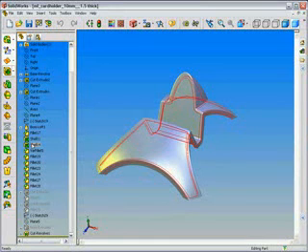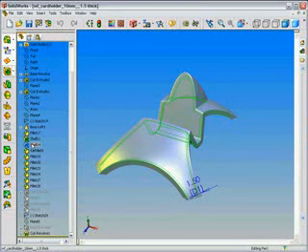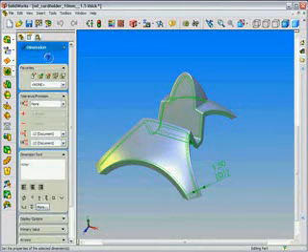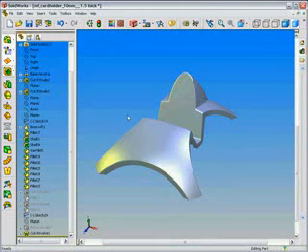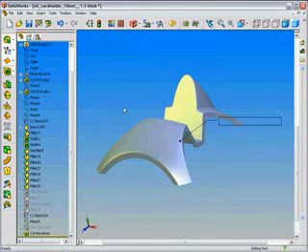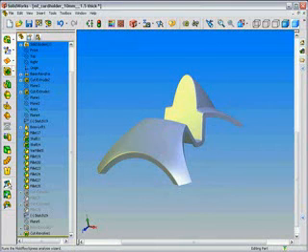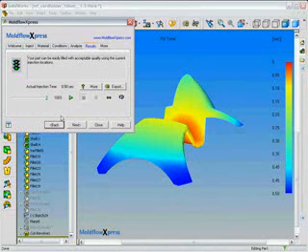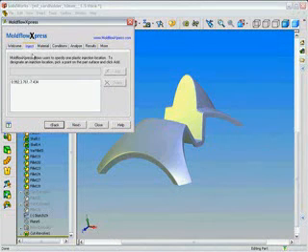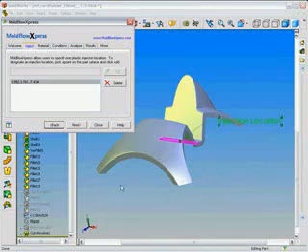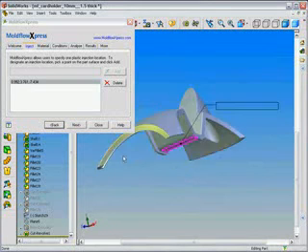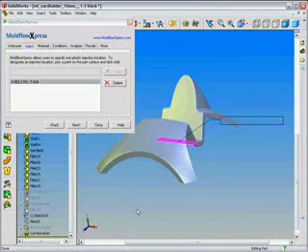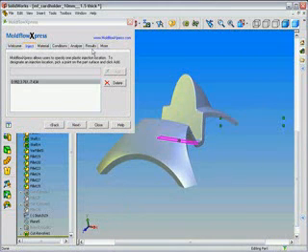In this variation of the model, we have a wall thickness of 1.5 millimeters, so we've actually thickened the material. We've also, as we launched the Mold Flow Express wizard, changed the injection location to more central to the part. We took some of the feedback provided by the wizard and made those changes.